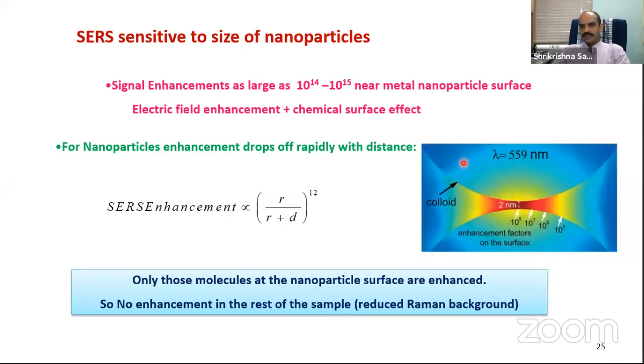When we are having this silver nanoparticle, and let's say this is another silver nanoparticle, what you can see is the electric field we have found theoretically, by simulation. The red color tells me that it is the most intense, and the blue color tells me that it is weak. So what you can see is that it is higher in between these two nanoparticles. It is of the order of 10 raised to 8.